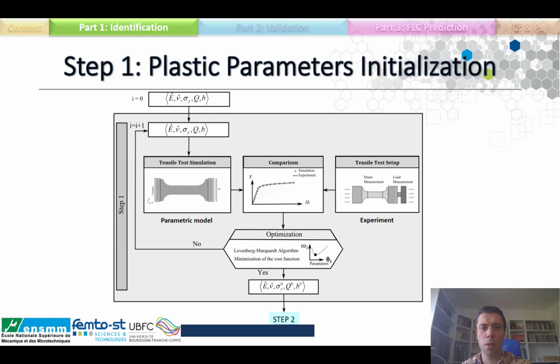The first step in the identification procedure is the initialization step. From the experimental tensile test, we obtain the elastic and plastic parameters. So it's here. Next, these parameters will be used as the initial input for a tensile test simulation. With a homemade optimization toolbox called MIC2M, the value of each parameter is modified to achieve the one with the least difference to those of experimental tests. When we arrive at this, it means that we have the suitable set of parameters to be used in the second step, which is the identification step.